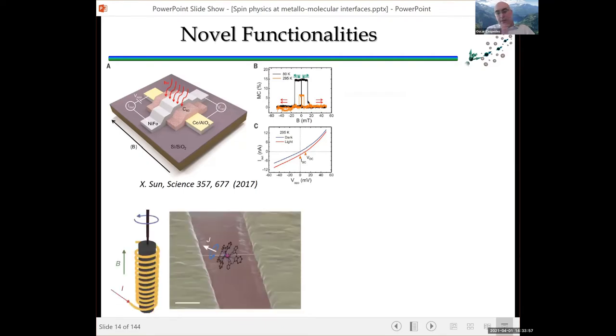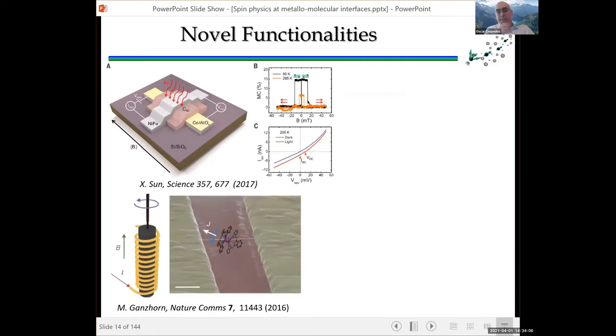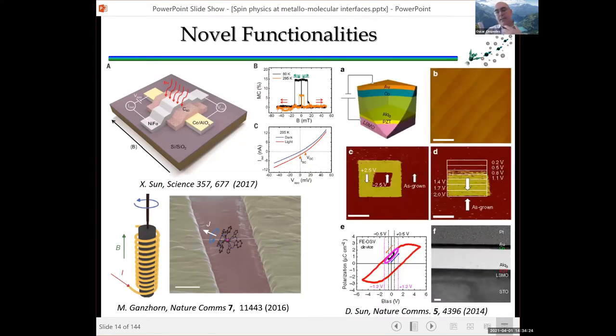And there are also, for example, the Einstein-de Haas experiments that Wernsdorfer did in the molecules for the conservation of spin and angular momentum, where the molecule can rotate depending on the actual spin ordering induced by the magnetic field. And therefore you can have changes in the quantum tunneling of the spins depending on the molecule orientation and the magnetic field. And we also have experiments like here from Sun et al, where they can manipulate the magnetoresistance of the molecular layer by using a piezoelectric substrate. So you combine magnetic and ferroelectric or piezoelectric functionalities in a multifunctional, not quite multiferroic, but hybrid multifunctional structure.